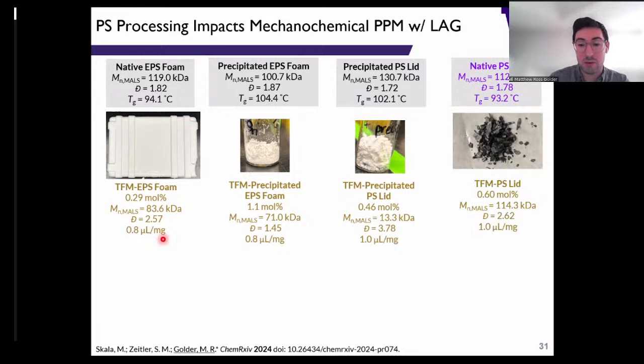This is in stark contrast to when we use the native waste. Actually, the native waste, we were able to get about 0.3 mol% tagging. So less than on the precipitated foam, but we see only about a 15 to 20% reduction in molar mass when we use the same 0.8 microliters per mg. But what was really interesting was that what we assumed would be the absolute worst substrate, the coffee cup lid with dyes, right? This is the only dyed plastic here. This worked the best. We saw virtually no change in molar mass, about 0.5 to 1 mol% tagging.